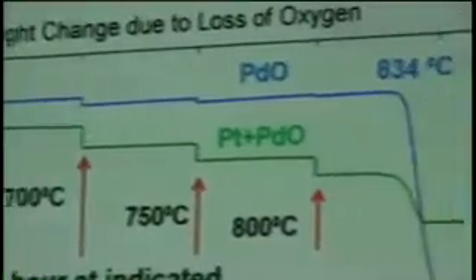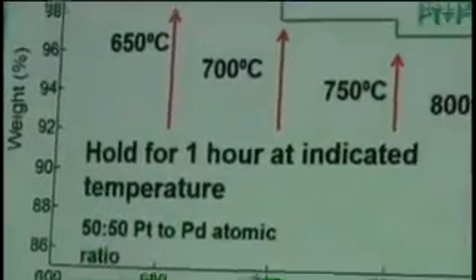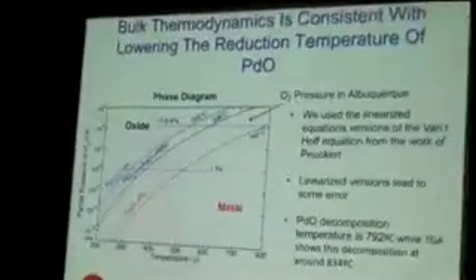We did the TGA, where we took platinum and palladium oxide, aged it, and indeed we saw the reduction. It's slow, so we had to hold the temperature constant to let the weight drop, and we could confirm that the weight change was consistent. And we can go from the thermodynamic calculation and get our phase diagram.